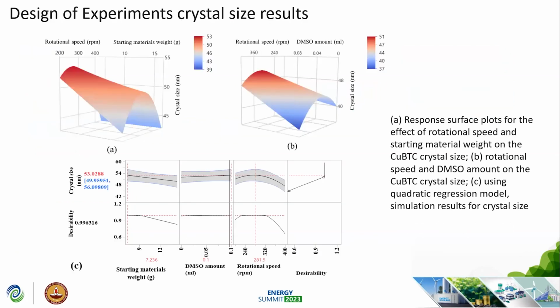In the design of experiments results, we can find the rotational speed, starting material weight, and DMSO amount will largely influence the crystal size of the copper BTC. As shown in the quadratic regression model, when the starting materials weight is 7.2, DMSO amount is 0.1 mL, and rotational speed is 280, we can get the largest crystal size, in the range of 49 to 56. Based on these results, we tested the copper BTC with the largest crystal size for hydrogen storage.